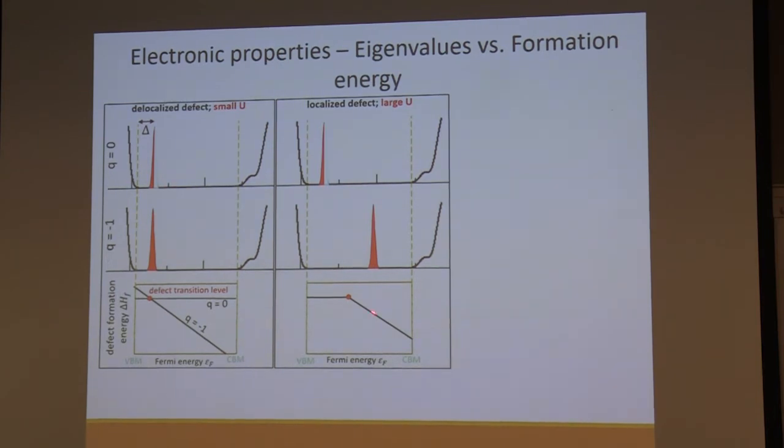You have your thermodynamic transition level. And then if the Fermi energy is here, you know how many are positively charged, how many are neutral, and how many are negatively charged, so you know how many free carriers there are. So you know the effect. Similarly, the chemistry may change. You put another electron in, so this is really just the defect level moving. But you could put an electron in the system, and there could be chemistry going on, where you have a large structural relaxation that binds, and something totally changes.